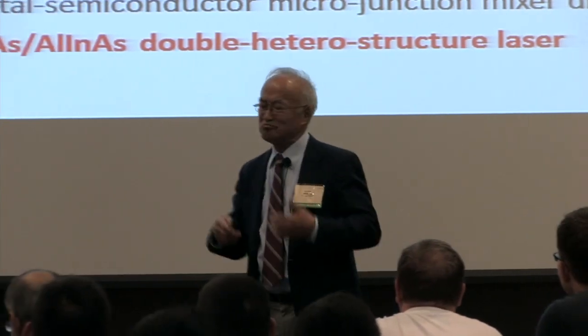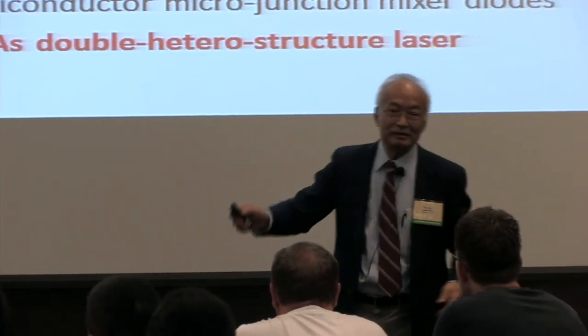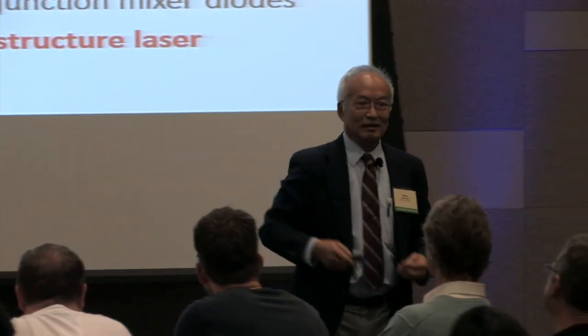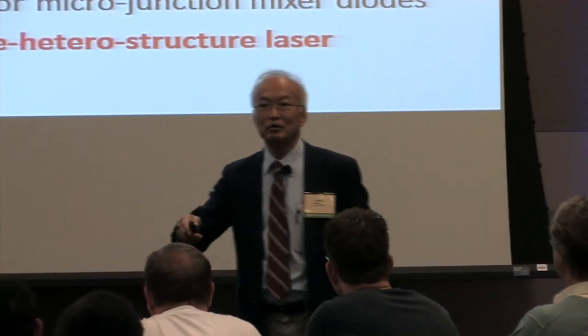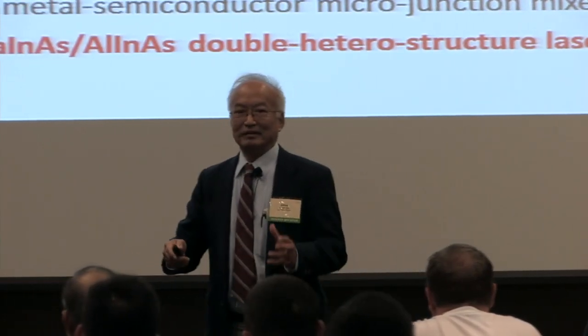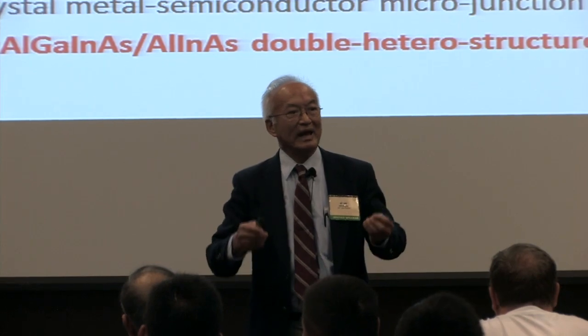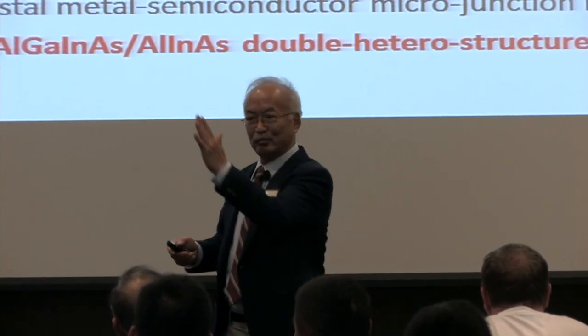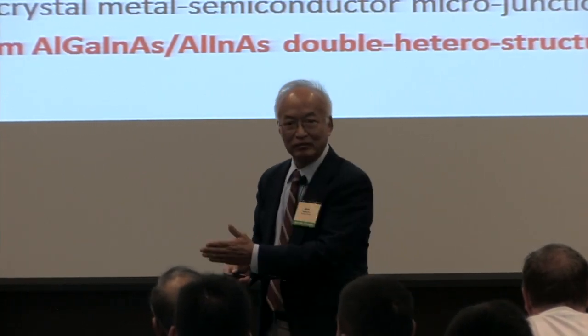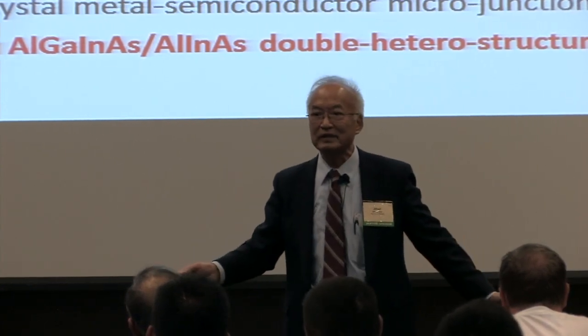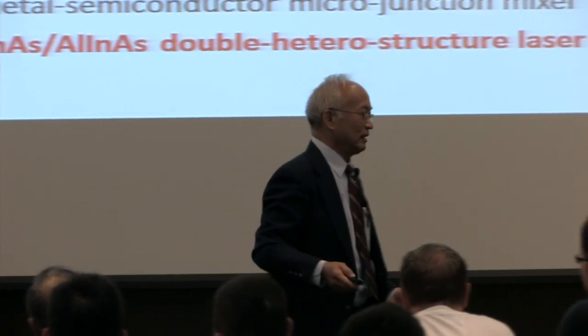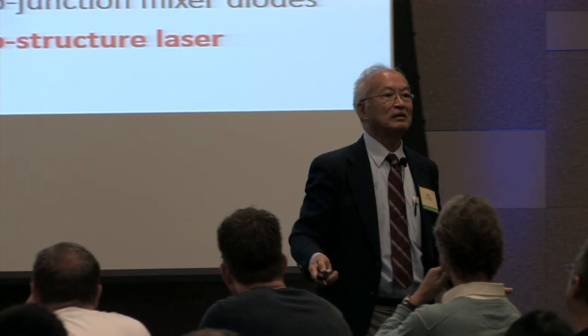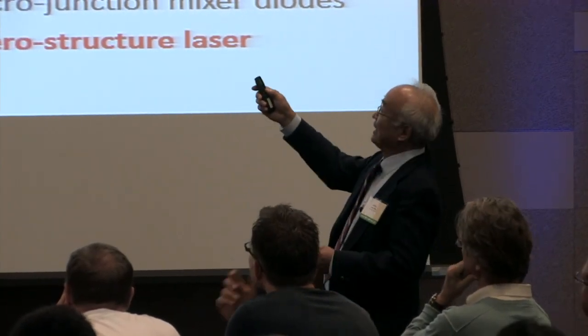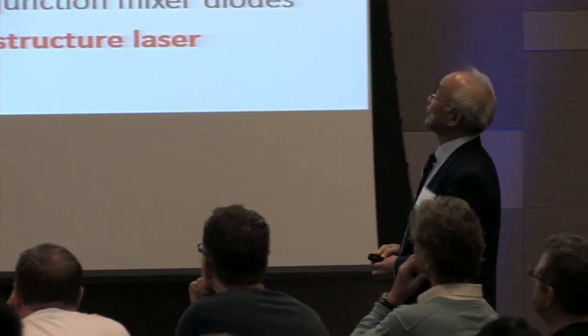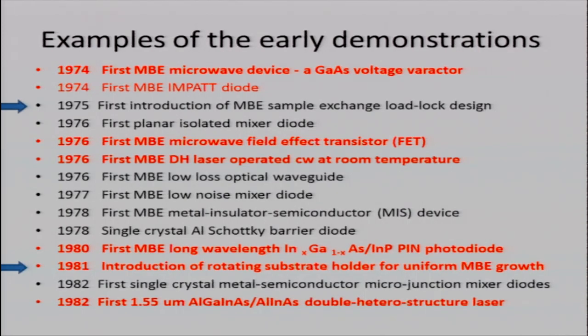Now, I have Franz Reinhardt across the hall from me. Franz Reinhardt said, oh, Al, don't get too depressed when you couldn't make that laser. It's not the end of the world. You try to demonstrate what MBE can do, LPE cannot do. What? He said, well, MBE can grow doping profiles any way you want to dope. You can dope exponential curve doping profile. You can grow low, high, low, abruptly changing within monolayers, changing the doping profile. No other crystal growth technology can do. And so you couldn't make the laser to lase, and let's do something with majority carrier devices, just electrons. So what I did is first, in 1974, demonstrated the first MBE microwave device called the gallium arsenide voltage varactor, that has a doping profile in the voltage varactor that is exponentially increased.